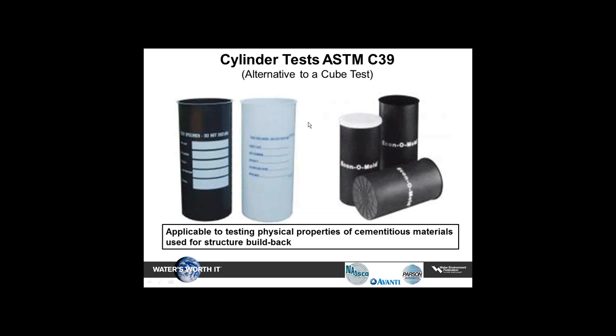As an alternative to this, some contractors prefer to use cylinder tests, very similar to what we do with concrete when we install concrete. Cylinder tests are defined under ASTM C39. It's an alternative to a cube test. And again, it's applicable to testing the physical properties of a cementitious material used for structure build-back.